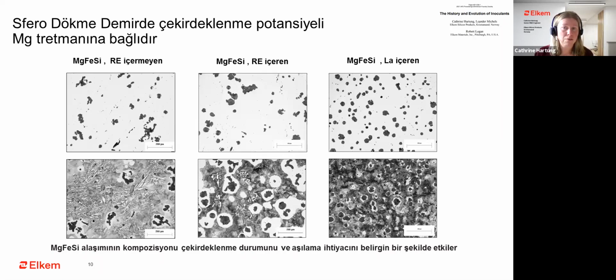The one to the left is the magnesium ferrosilicon without rare earth, very commonly used in Europe. The one in the middle has some rare earth, while the one to the far right is a LAMET type magnesium ferrosilicon. And as you can see, the two examples to the left have both passed below the metastable line. So you have carbides in the structure and very poor graphite. While in the case of LAMET, you have been able to have the solidification between the metastable and the stable line, and you do not have any carbides.